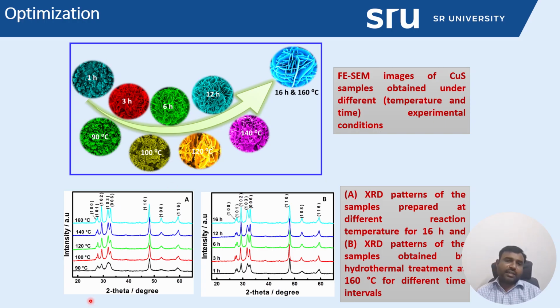Further, the XRD was investigated for all the samples prepared under the optimized conditions, from 1 hour to 16 hours. See here, at the lower time of 1 hour, all the peaks are very broad. When increasing the time, the crystallinity of the peaks gradually increases up to 12 hours. After that, there is not much change; all the peaks have a similar pattern and do not give any impurity peaks. Similarly, when increasing the temperature, at 90 degrees we can see very broad peaks in the lower region from 25 to 35 degrees. So it indicates that the reaction does not complete, hence we are obtaining very low, broad peaks.